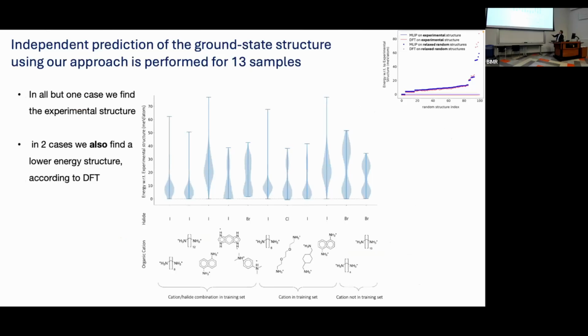And we could reapply this. These violin plots are summarizing this entire distribution. This violin plot extends here to the maximum value. The bubble here is around the mean. That would be something like these samples that are sampled from the index of 20 to 80. And eventually you get to the ground state. And this bottom one, the ground state, in all these cases has an experimental counterpart. So we're comparing our independently predicted structure to what's been available experimentally.